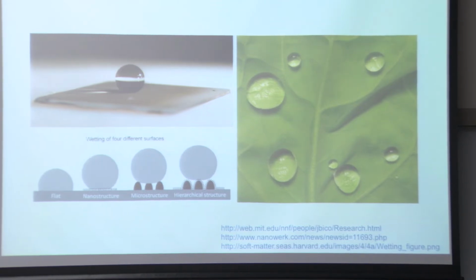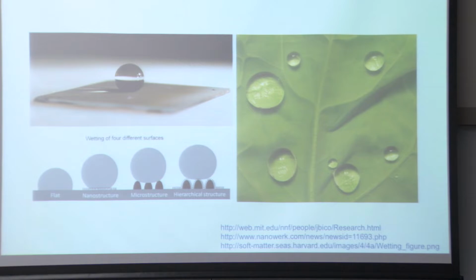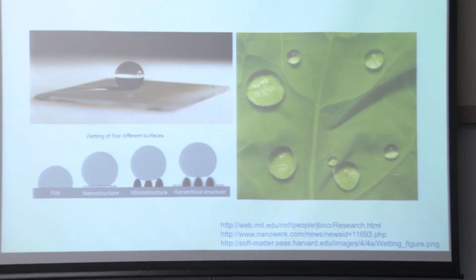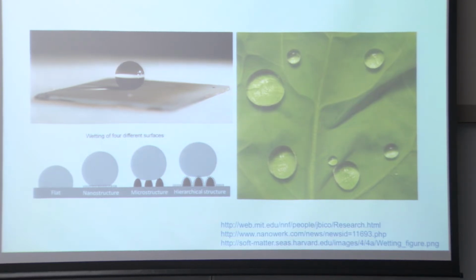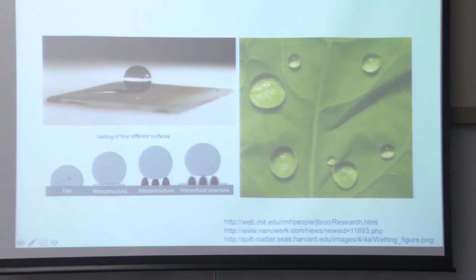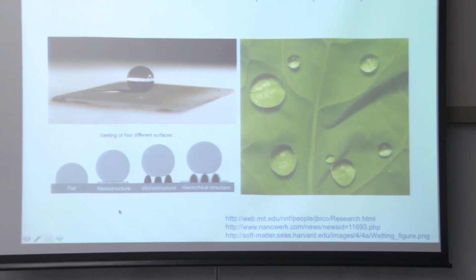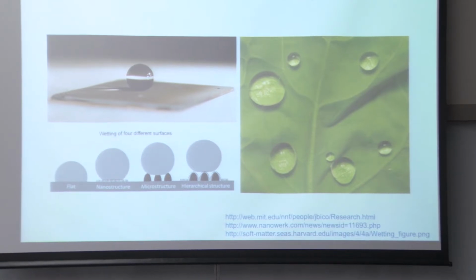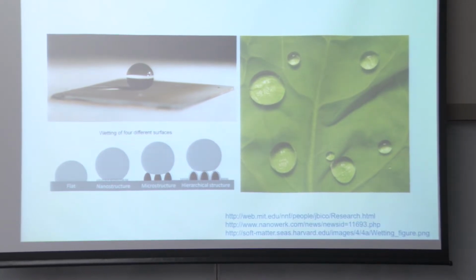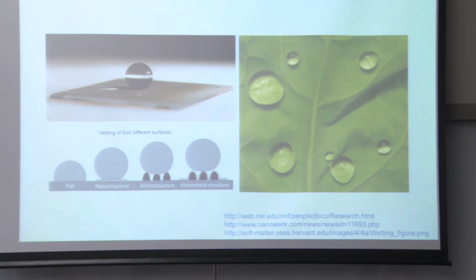It has to do with the ability of wetting that is dependent on the surface hierarchy of nanostructuring and roughness. In an ideal Young's equation, where you have an essentially flat film, the work of adhesion is aided by a strong interaction on a surface. On the other hand, the failure of adhesion can be related to the failure to form a continuous line tension or surface tension, and in the presence of trapped air results in this superhydrophobic effect.